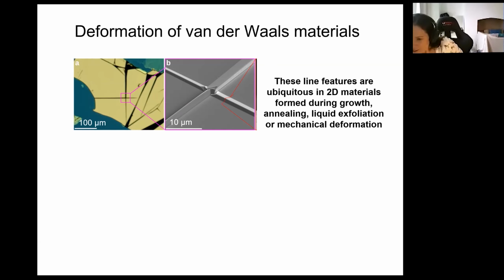We've done the angle of incidence. Can you use doped graphene? Not for the energies that we're using here. The energies of the incident ions are much, much too high. Again, that's why we don't see a lot of implantation. But I know that other groups have been able to do implantation of the graphene structures by using implantation energy of the order of eV, whereas here we're using energies of keV. Although I agree, implantation of argon is probably unlikely. Although, I don't know, maybe in thicker samples you might get bubbles.